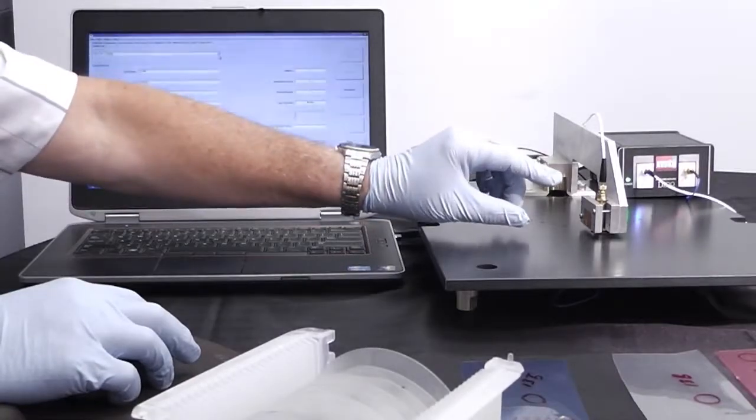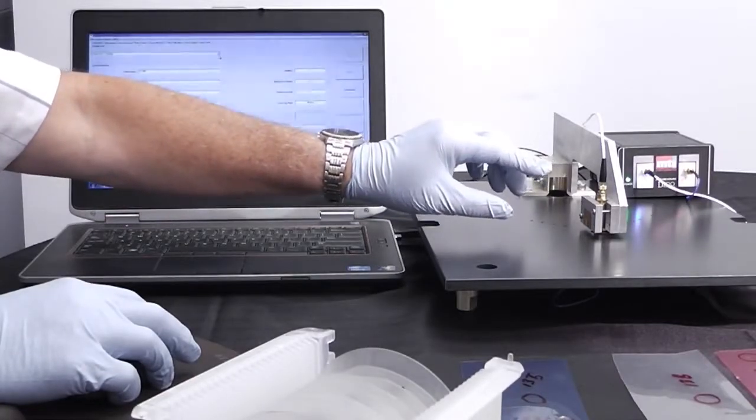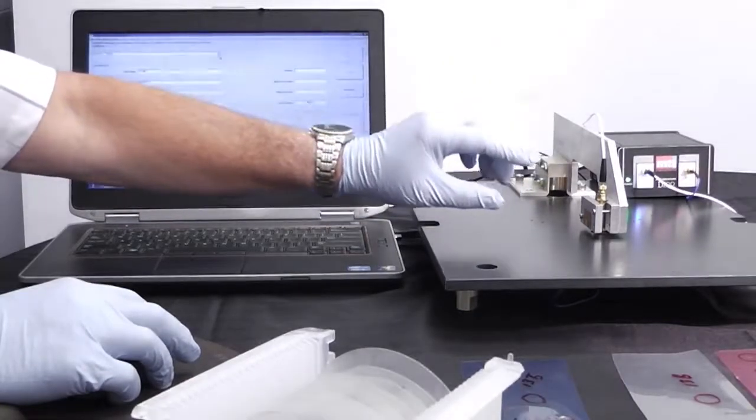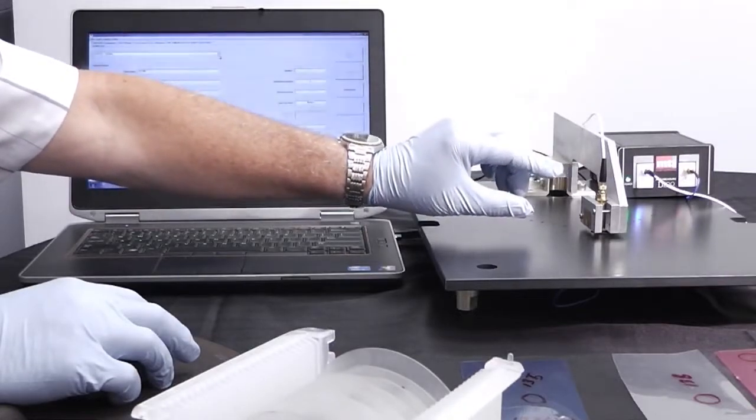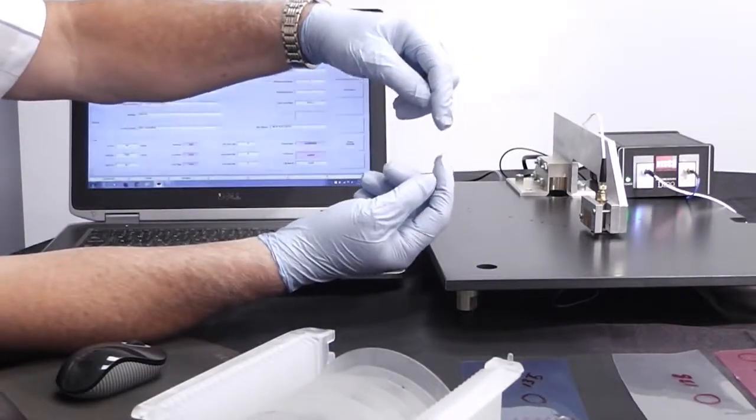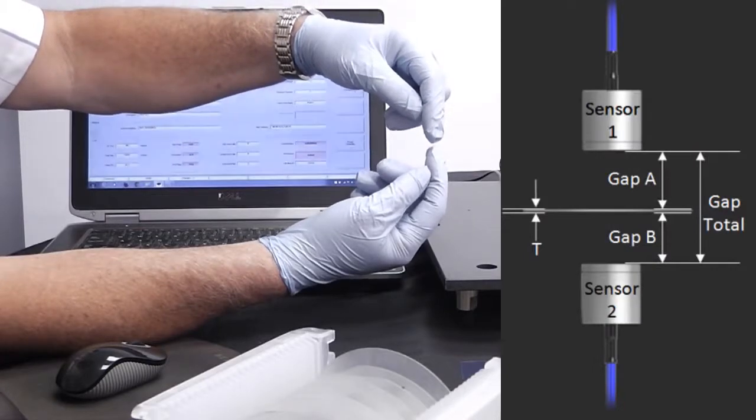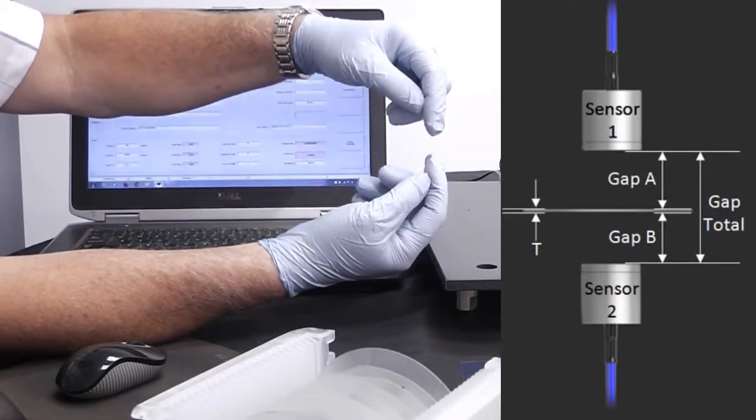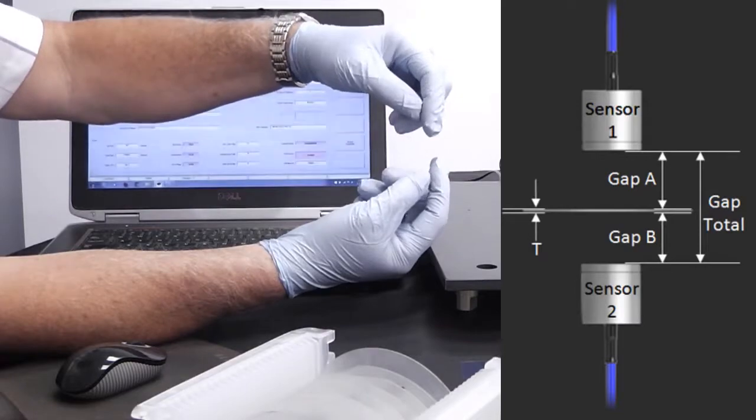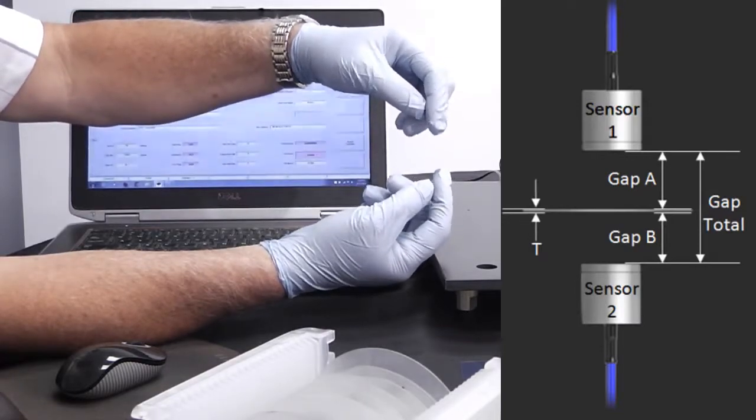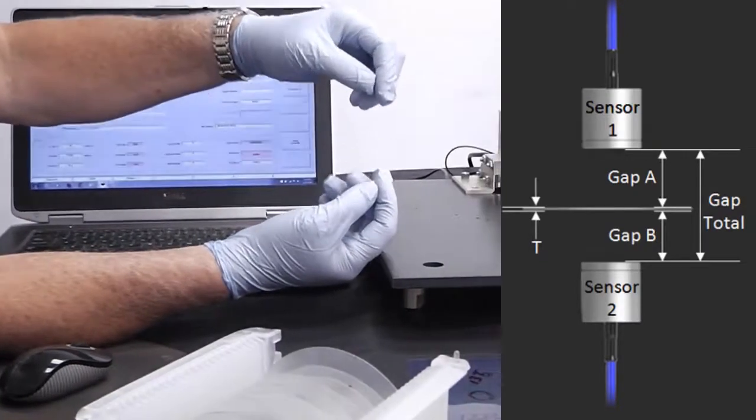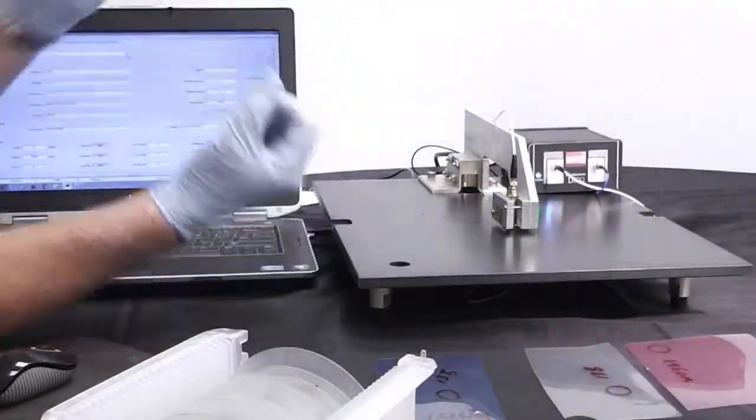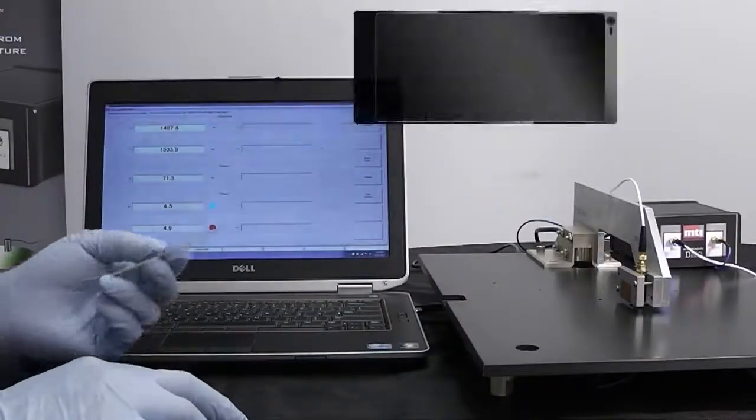For measuring the thickness of dielectric materials or non-conductive materials, the first thing we have to do is set the probe gaps. What we want to do is to have our two probes specified distance apart and that distance is going to be two times the range. The probes each have the same range, plus the thickness of the target and then you're going to come in a little bit closer.